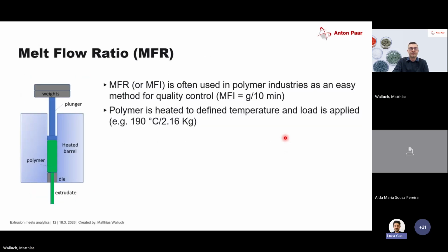I already mentioned the MFR or MFI, the melt flow rate. This is a very commonly used way to characterize materials because it's very easy. We take a polymer, put it into a barrel, heat it up, melt it, and use a weight to press it through a defined nozzle. In the end, everything is defined for the different kinds of polymers. So we have a certain temperature, in this case, for example, 190 degrees, and we have a certain weight.